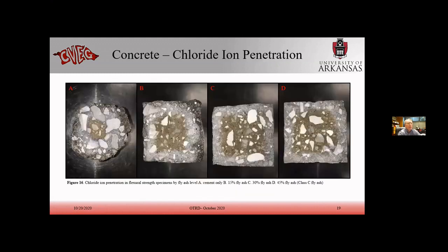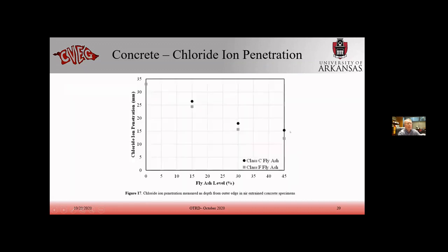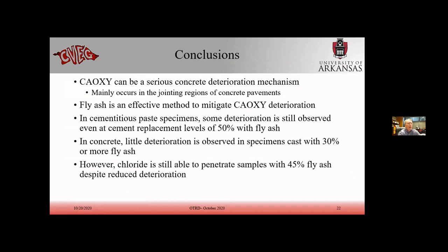So we did a little bit of chloride ion penetration. I'm running out of time, but this started off as a prism, and then over time, this was the core that was left, and you can see that the dark gray circle is the ion penetration over time, and as you increase fly ash, that distance is less and less. So I'll move on past this and just end with our conclusions.